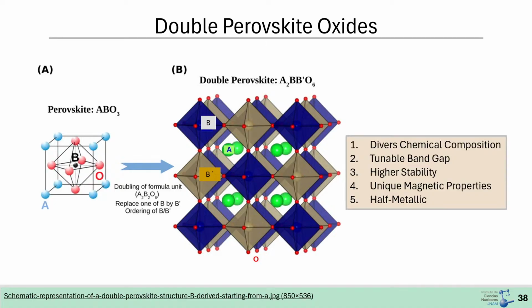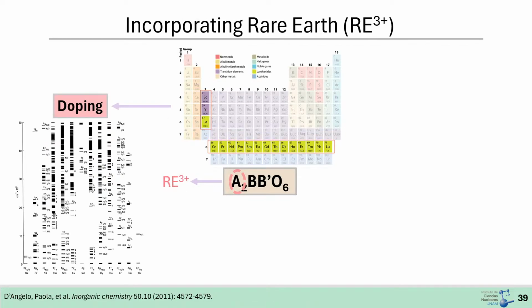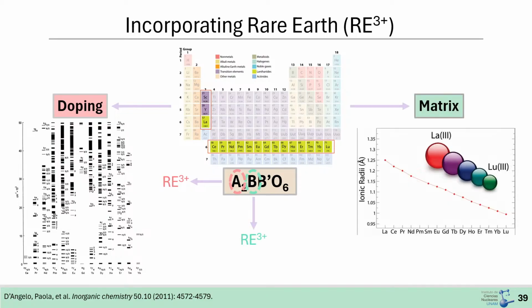And they have diverse chemical composition, tunable bandgap, high stability, unique magnetic properties, and half metallic behavior. Besides, we can dope them, for example, with rare earths and take advantage of the unique electronic properties of the rare earths. We can use rare earths as a matrix. We can take advantage of the magnetic properties, for example, or take advantage of the different radius, and that way manipulate the bandgap, basically changing the composition.